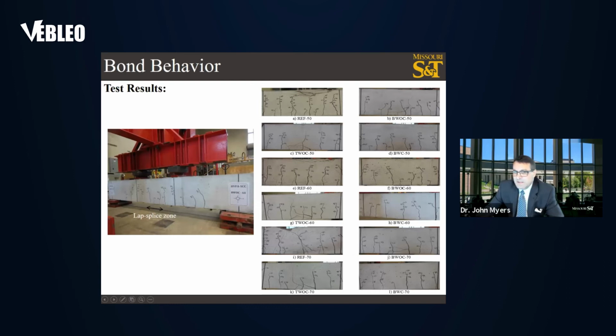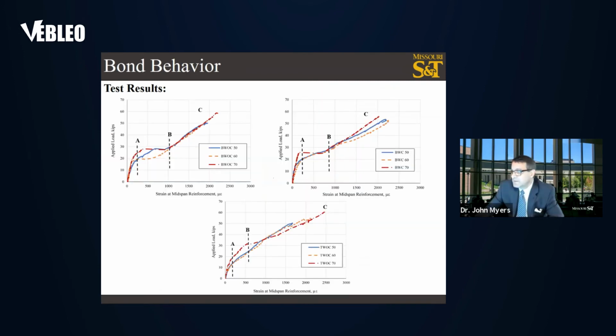And here you can see the splitting failure along the length of the horizontal splice, and the crack patterns experienced by the splice beams without confinement were essentially identical. Confined beams with transverse stirrups in the splice zone had a slightly different crack pattern than beams without confinement.